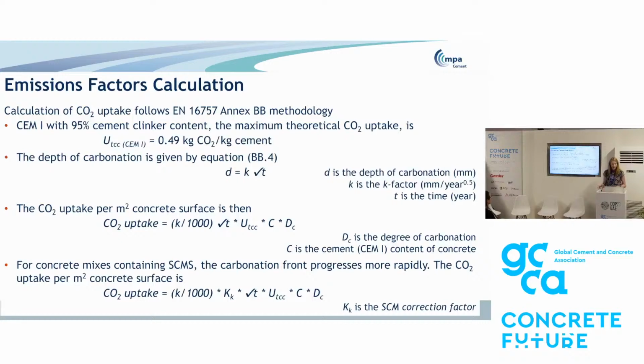So this summarises the methodology for calculating the emission factor in EN 16757. To calculate the uptake, you start with the maximum theoretical carbonation of a CEM I cement with a 95% clinker content. So that's 0.49 kilograms of CO2 per kilogram of cement. We then multiply that by the depth of carbonation. So this is how far into the concrete the carbonation has moved, and that's been found through testing concrete samples. And Miguel mentioned that increases with the square root of time.